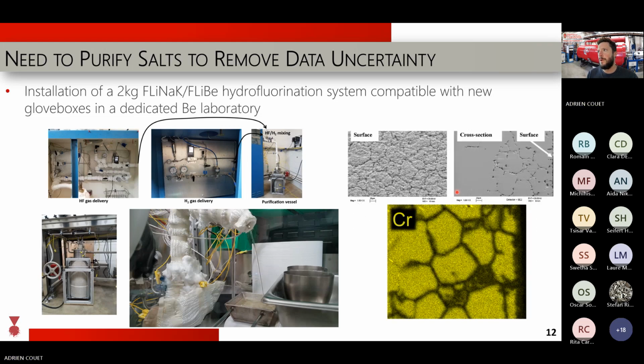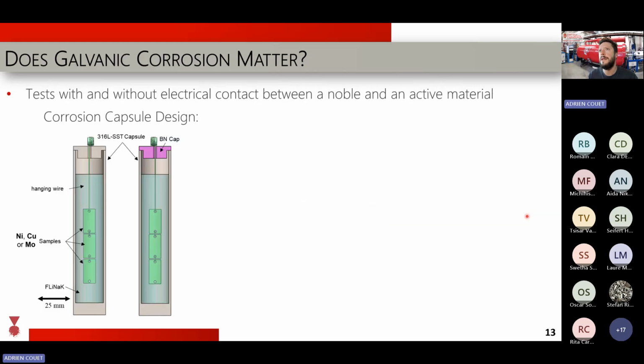Well, dissolution of chromium from the grain boundaries. It's a well-known effect. Chromium fluoride is very stable, like chromium oxide, right? But it dissolves, of course, in the salt. So you have this dissolution path. You're losing your chromium from the grain and the grain boundaries, and you see a weakening of the grain boundaries because of that. So that's a well-known observation of chromium-bearing materials in molten salts.